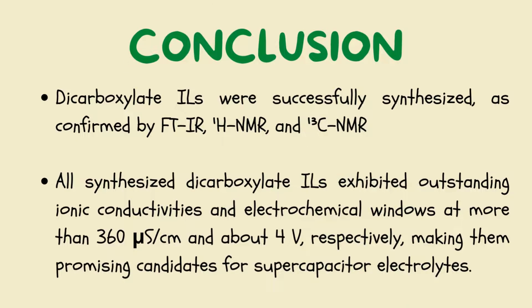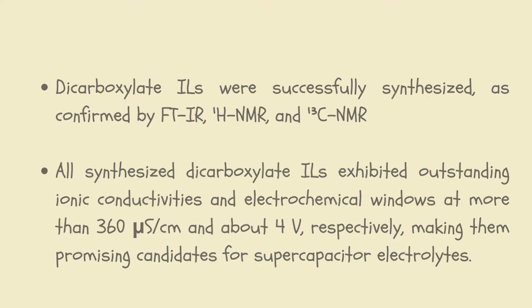To wrap it all up, dicarboxylate ILs were successfully synthesized as confirmed by the FTIR, proton NMR, and carbon NMR spectroscopy, and all synthesized dicarboxylate ILs exhibited outstanding ionic conductivities and electrochemical windows at more than 360 microsiemens per centimeter and about 4 volts, respectively, making them promising candidates for supercapacitor electrolytes.